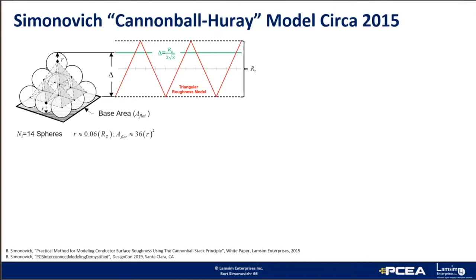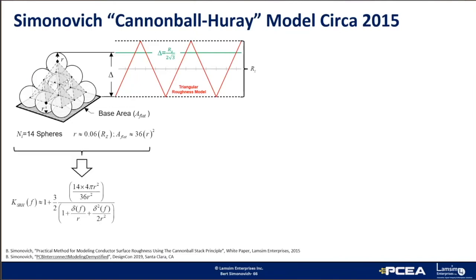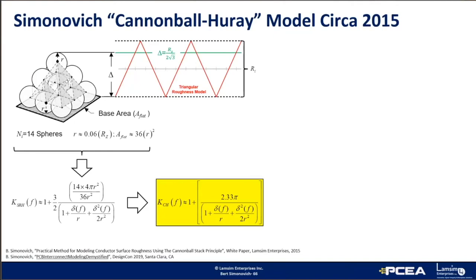The height of the cannonball stack is equal to delta using my triangular roughness model. Through this simple geometry and a little bit of algebra, we can approximate the radius of a single sphere equal to 0.06 Rz and the base area equal to 36 R squared. Because the model assumes the ratio of A mat to A flat equals 1, and there are only 14 spheres total, the Cannonball-Huray model can be simplified to this equation. And as you can see, the radius is the only parameter needed, which can be easily determined by Rz.